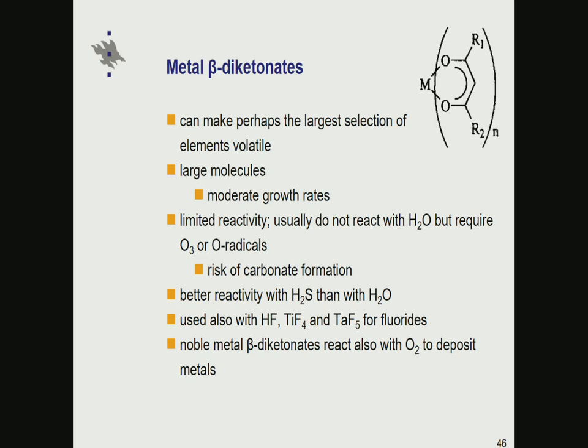Metal beta diketonates have been around essentially from the beginning of ALD, actually even before ALD was developed, when metal beta diketonates were used for other purposes. I think this is a group of compounds which offers you the widest selection of volatile metal compounds. Essentially all metals can be made volatile by choosing beta diketonate ligands, which are bidentate oxygen donor ligands, making 6-membered rings, very stable molecules.